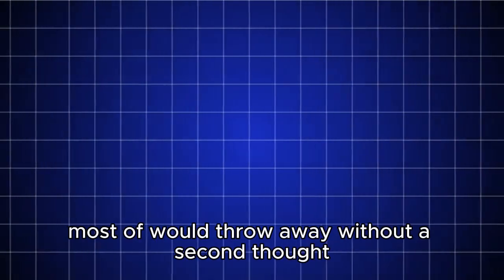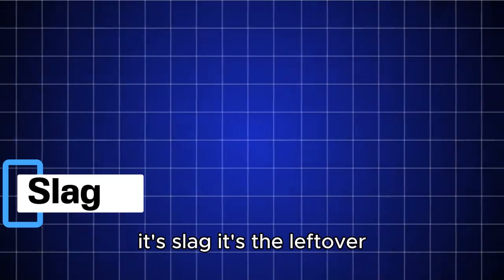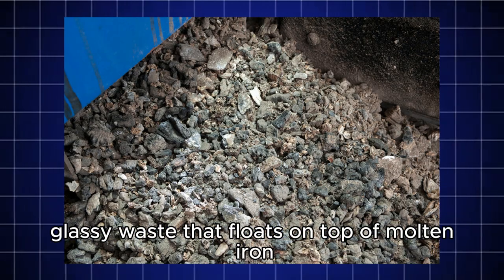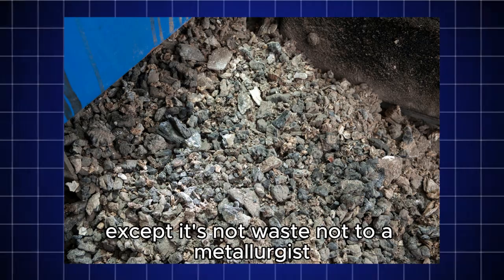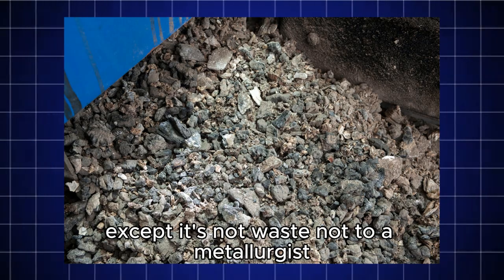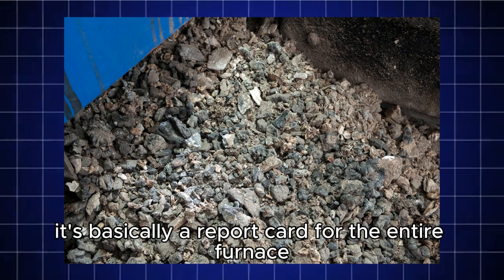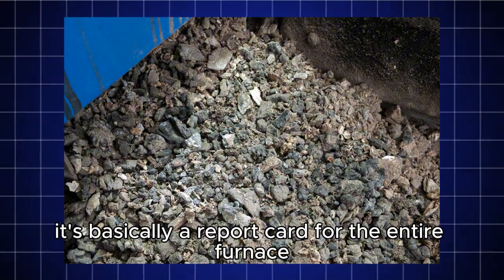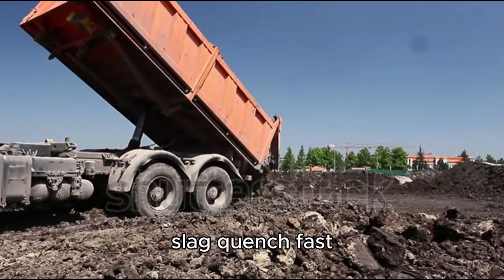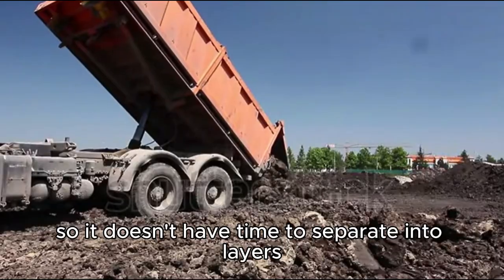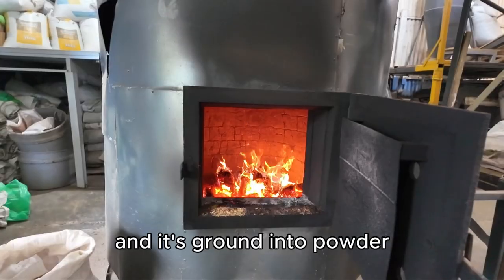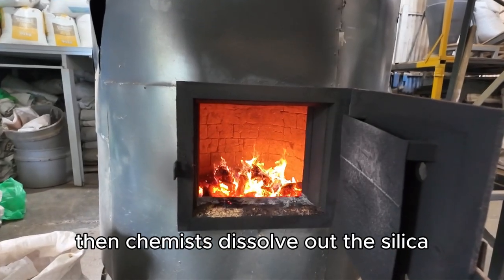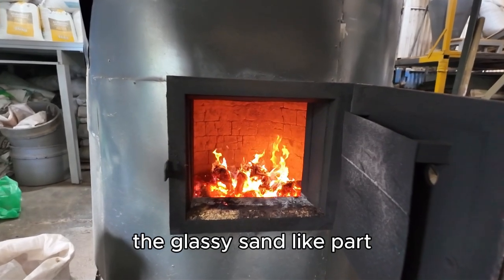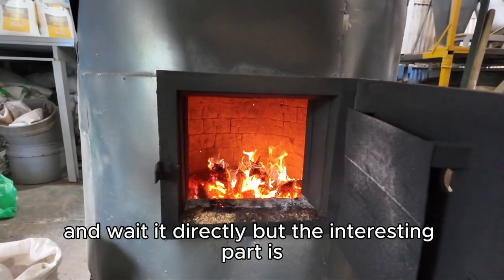Now, here's some material most would throw away without a second thought. It's slag. It's the leftover glassy waste that floats on top of molten iron. Except it's not waste. Not to a metallurgist. It's basically a report card for the entire furnace. Slag is quenched fast, so it doesn't have time to separate into layers, and it's ground into powder. Then chemists dissolve out the silica, the glassy sand-like part, and weigh it directly.